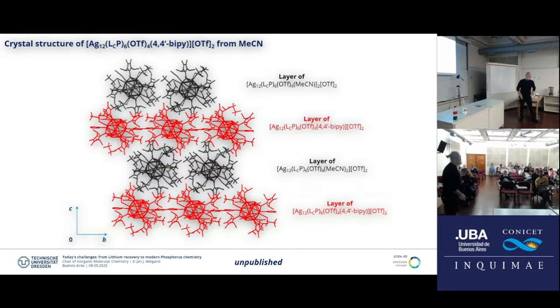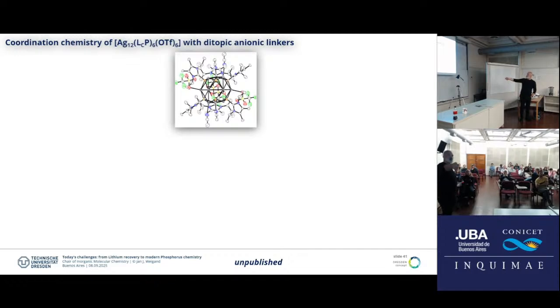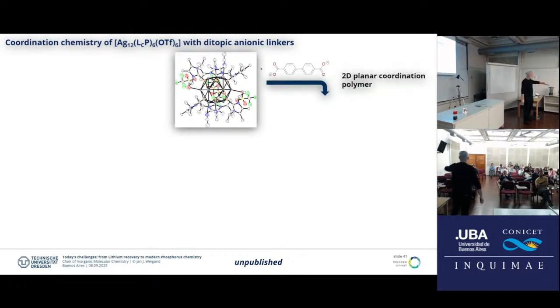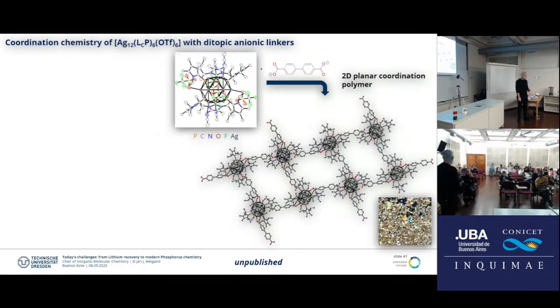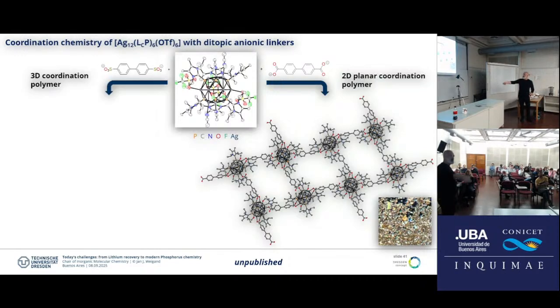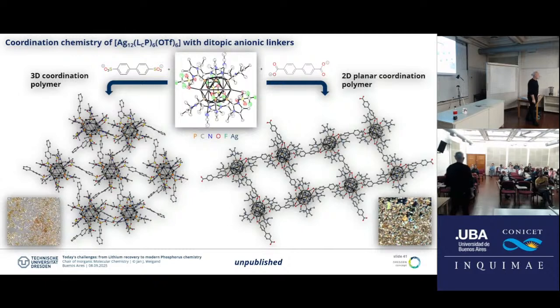Now, of course, you need to have a different linker. So we've done ditopic ones, for example, carboxylate, which gives you more or less like a planar, and that is prone to give you 2D. And this is a molecular structure. There is no simulation, nothing. It's really the crystal structure. And of course, if you go here, tetrahedral, you would make the 3D, and that works quite nicely. And this is the 3D coordination polymer, which has the corresponding silver cluster as the nodes